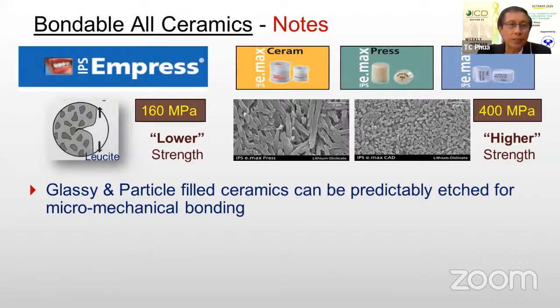So these are some of the summary on the ceramics that we've spoken so far, the all ceramics. I'm going to use the Ivoclar Vivadent range because that's the one that I'm most familiar with. If you use that range of either a leucite infiltrated glass ceramics or one of these lithium disilicate formulations, the IPS Empress is considered at 160 megapascals a lower strength ceramic, whereas the E.max Press and the other E.max material at 400 megapascals are the highest strength material. So the glassy ceramics can be predictably etched for micromechanical bonding.